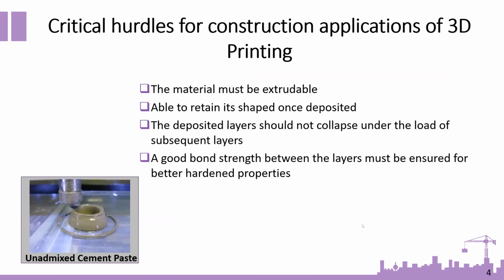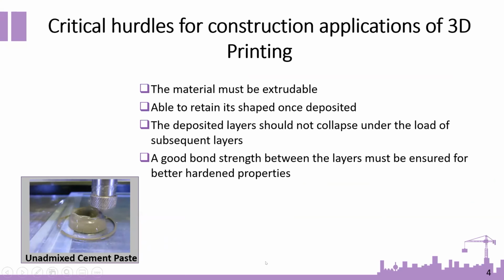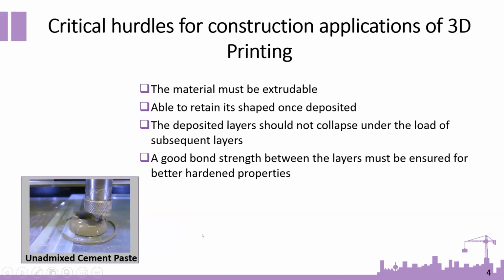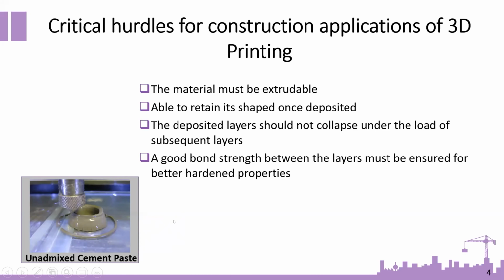But yet, there are a number of critical hurdles. The material must be extrudable. It should be able to retain its shape once deposited. The deposited layers should not collapse under the load of subsequent layers, and a good bond strength between the layers must be ensured for better hardened properties. Our results show that unadmixed cement paste is simply not printable. So what's the solution? The answer is additives or admixtures that can be added to the cement paste to make it printable.